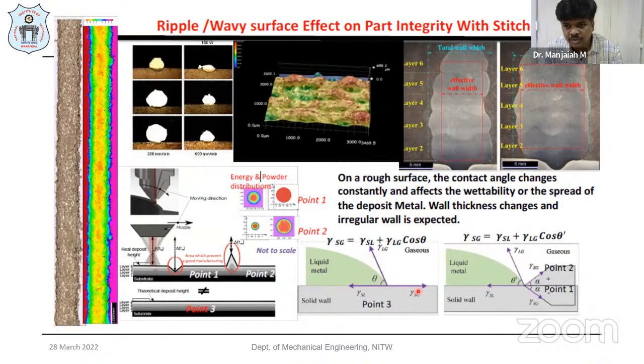And as well as the wall thickness changes, and an irregular wall is expected. You can see these kinds of irregular wall layers are going to be expected if you are not optimizing the process window or controlling the feedback signals of the melt pool in each layer. We assume that the layer is uniform, but there may be these kinds of variations in the offset distance. The area where we are expecting good manufacturing may be the valley or the peaks.